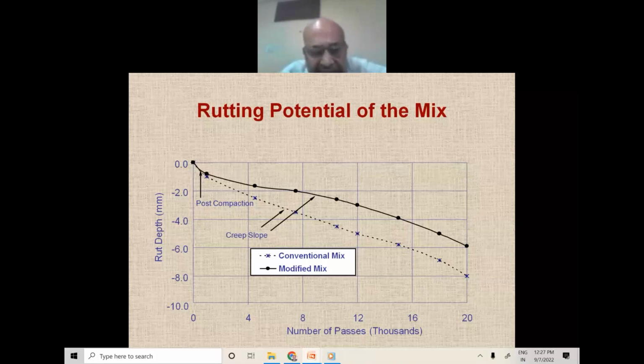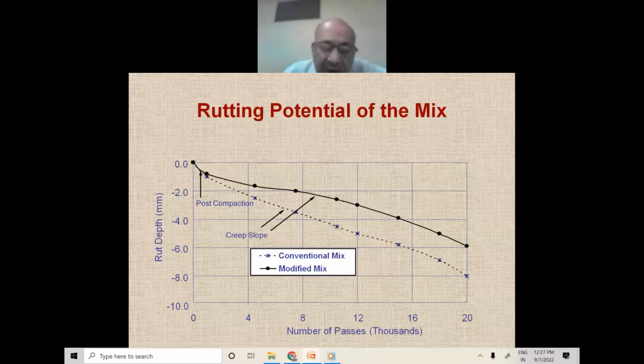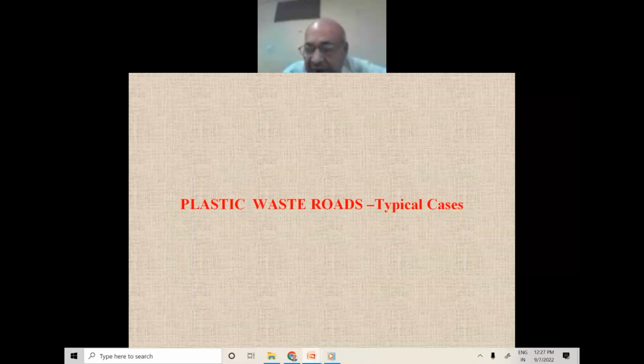Rutting studies on a bituminous mix can be carried out by the Hamburg wheel tracking test, where a loaded wheel is moved over a slab, a beam specimen, and you can see the condition of the beam specimen after the rutting test. The left hand side specimen is for unmodified mix not having plastic waste, and on the right hand side is the mix having the plastic waste. So you can say that the rut depth is very high in the mix without plastic waste and less in case of the mix with plastic waste.